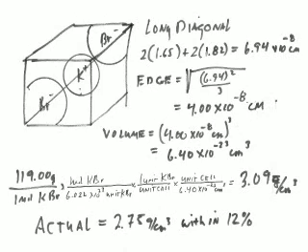So our theoretical value for the density of potassium bromide is 3.09 grams per cubic centimeter. The actual density, 2.75 grams per cubic centimeter, is off by about 10%. So we're getting basically 2 significant figures in our calculation, which actually isn't too bad considering all the assumptions and all the approximations we made in trying to create our calculation.